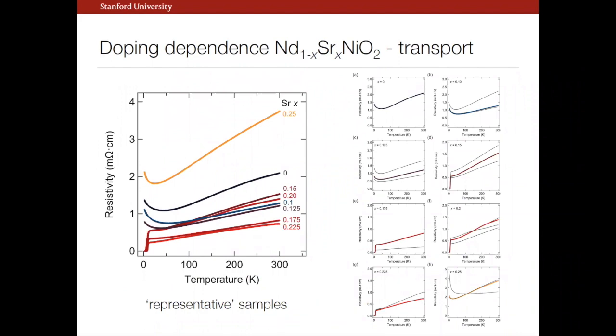So doping dependence of transport. So first we could just talk through the representative samples. It's rather strange. In the cuprates, you go through many orders of magnitude as you go forward into the Mott insulator. Here's x equals 0. It goes down and back up, but the whole variation is fairly narrow in the vicinity. Representative, again, modulo this variation, I showed you here, hopefully.